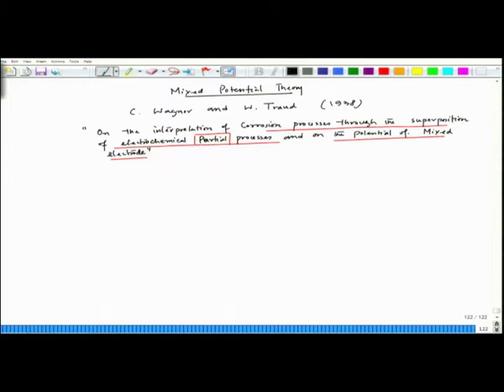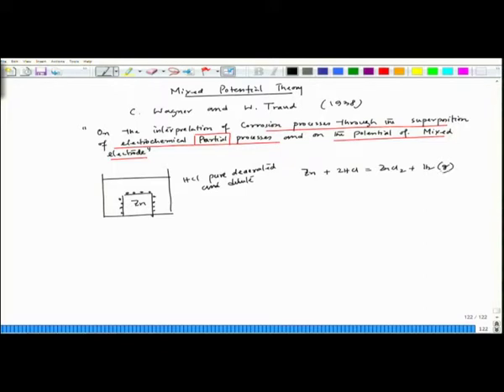Now, if I could get back to the corrosion of zinc in pure deaerated dilute HCl solution. So, this is a beaker where I have put HCl, which is a pure, deaerated and dilute solution. In that case, I have put a zinc piece, and immediately I could see that hydrogen bubbles will form on the metal surface. Now, if I analyze this, the actual reaction that takes place is this.